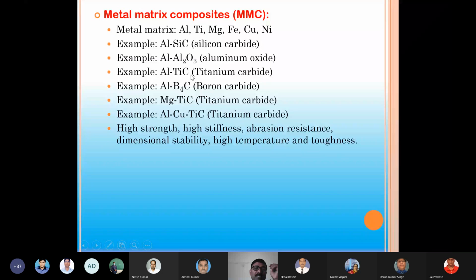The B4C, I think Arvind has worked on this B4C. If boron carbide is added as a reinforcement in the aluminum matrix, we can have boron carbide composites. If titanium carbide is added into magnesium as a matrix, we can have magnesium matrix composites. And copper alloy, this is duralumin. Aluminum and copper together. If copper is 0.43 to 0.48, this comes under what we call duralumin.